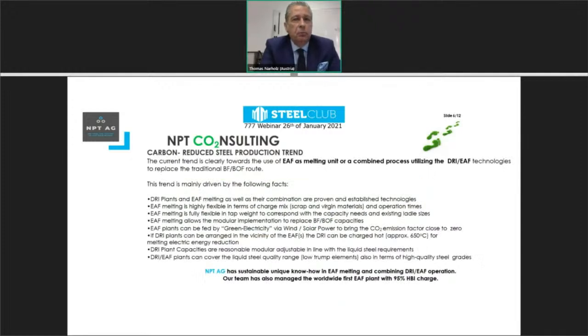What we have seen in a lot of projects where we are involved and trying to implement this in different plants is that more and more the DRI and EAF combination is, let's say, the most favorable solution at the time being. Does not mean that new technologies will not come up and change the equation a little bit, but the fact is that this combination is proven and established technology, and that the EAF is extremely flexible in the charge mix. So it can be combined in different ways. It can be cold, hot, always depending on the layout which is possible to implement. The EAF is also fully flexible in tap weight, to be adjusted whether you would like to replace the full capacity of an existing plant, or to increase or decrease your capacities.